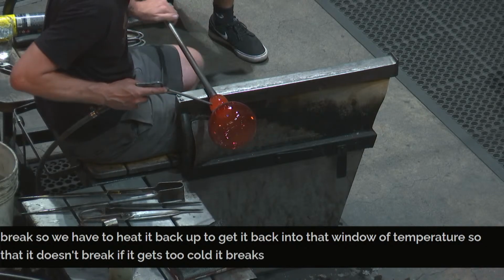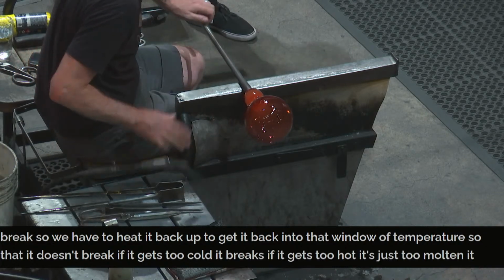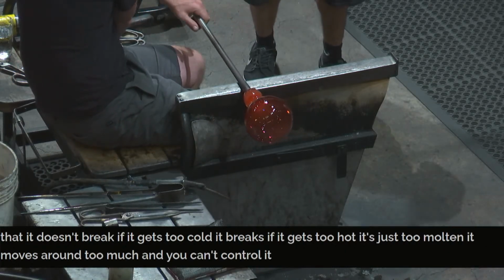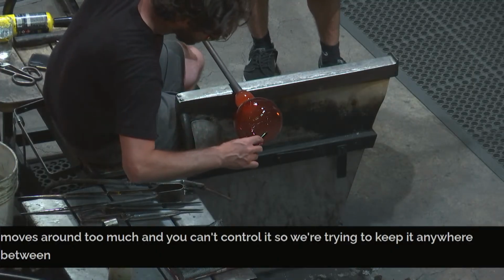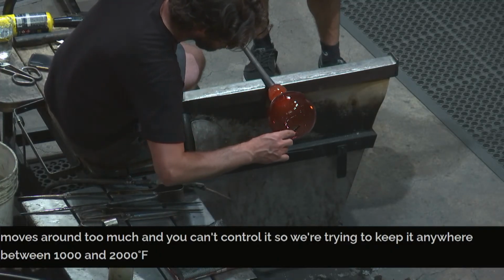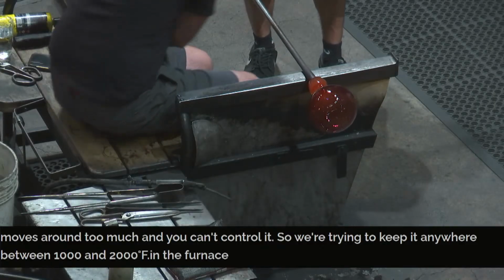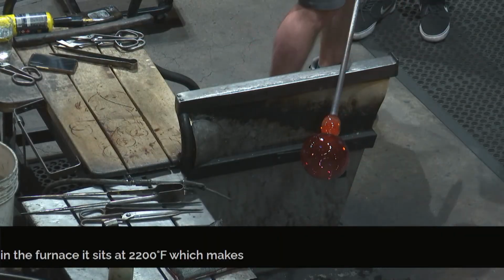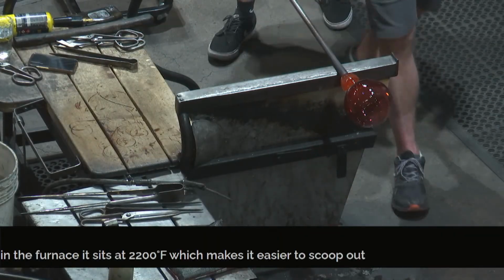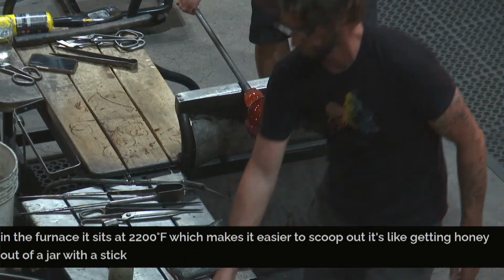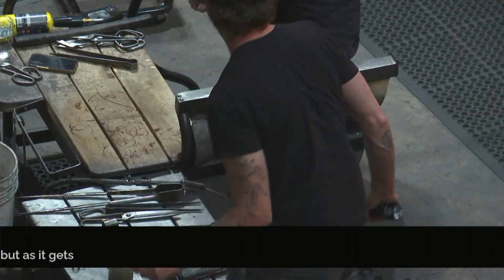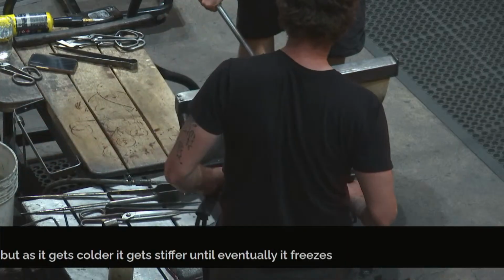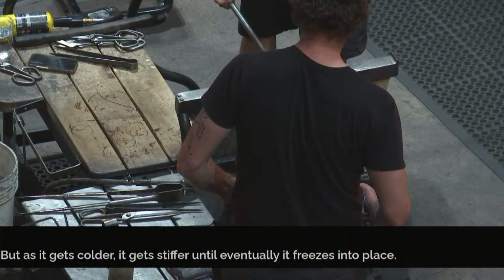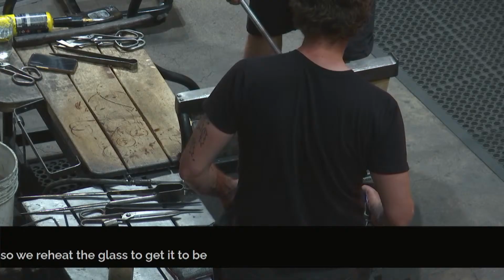If it gets too hot, it's just too molten. It moves around too much and you can't control it. So we're trying to keep it anywhere between 1,000 and 2,000 degrees Fahrenheit. In the furnace, it sits at 2,200 degrees Fahrenheit, which makes it easier to scoop out. It's like getting honey out of a jar with a stick. But as it gets colder, it gets stiffer until eventually it freezes into place. So we reheat the glass to get it to be more molten and more malleable.